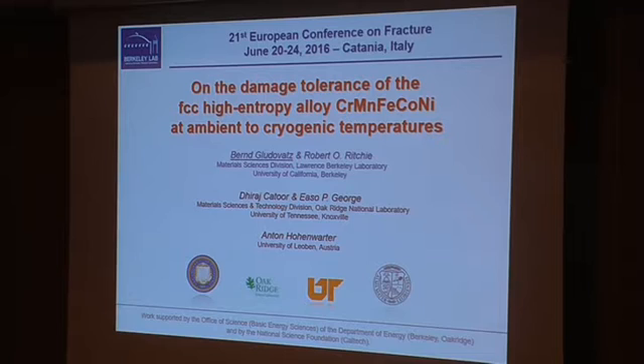which we have of course done for at least 10 different such profiles on both room temperature samples and liquid nitrogen temperature samples, and ended up with a crack tip opening displacement of about 57 microns for the room temperature sample and 49 microns for the liquid nitrogen sample, which using the relation we can then back calculate into a J, and the standard J-K equivalent gives us basically a crack initiation toughness at a delta K of 0, basically the first physical crack extensions, where we measured 190 and 200 MPa root meter at room temperature and liquid nitrogen temperature respectively, which matches quite well the numbers that we have measured globally.